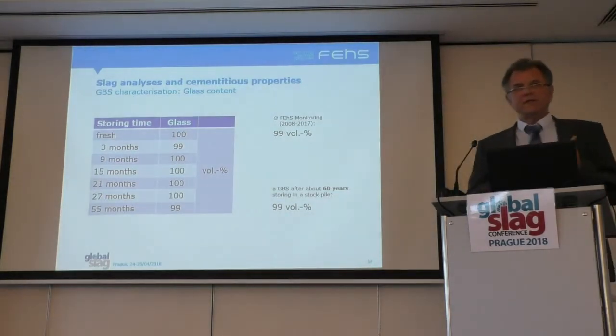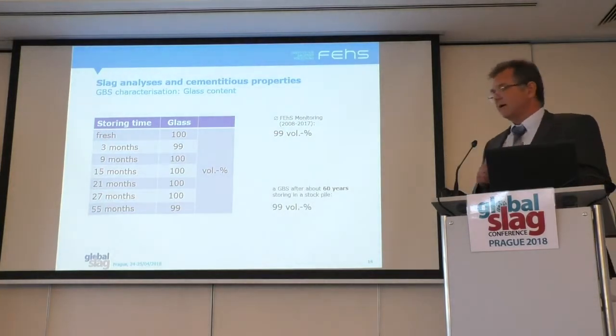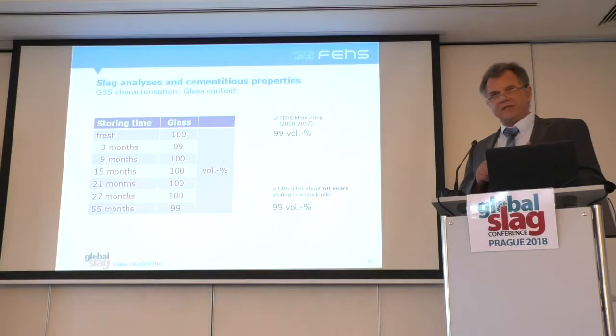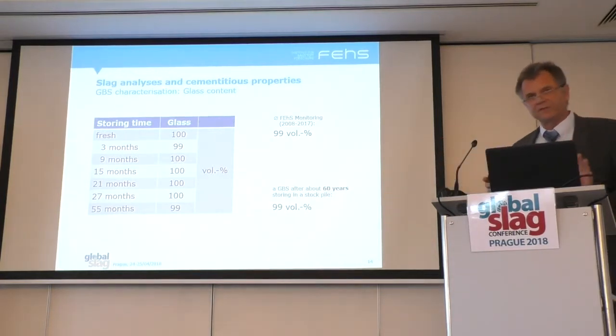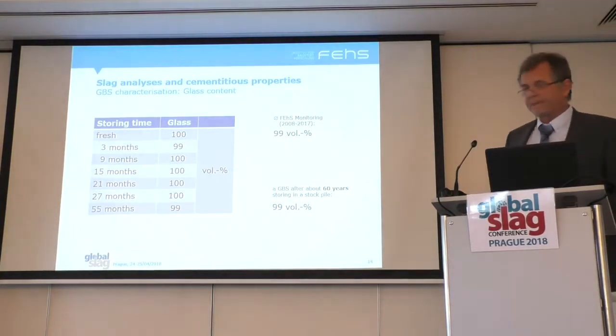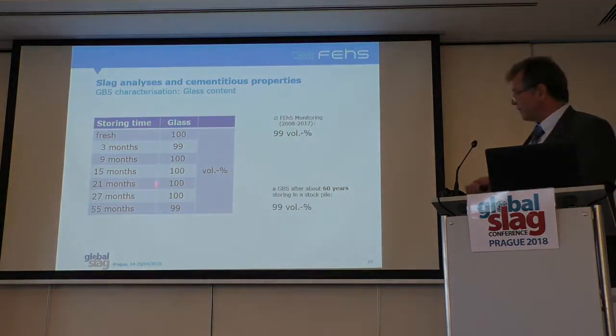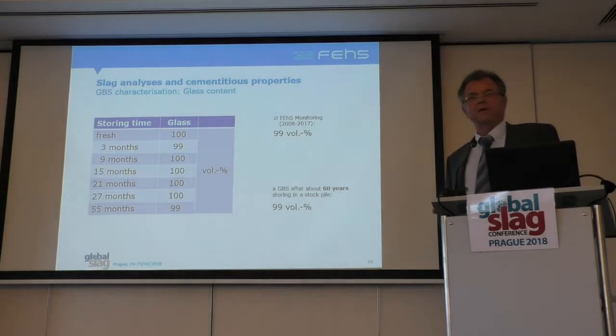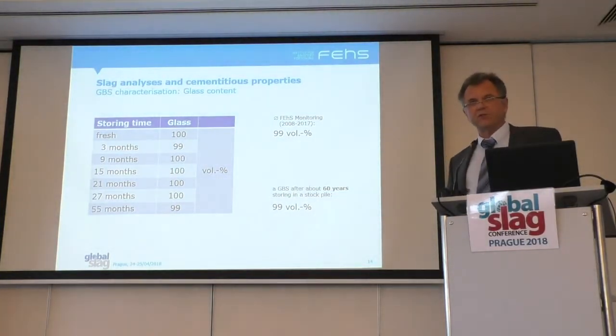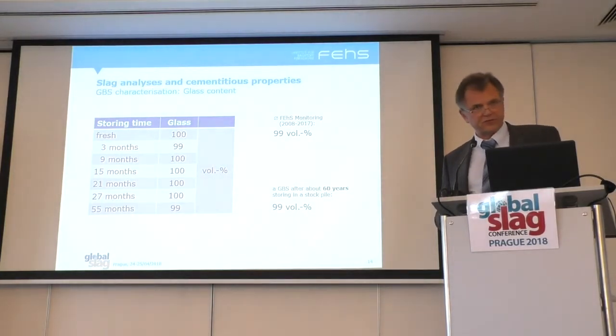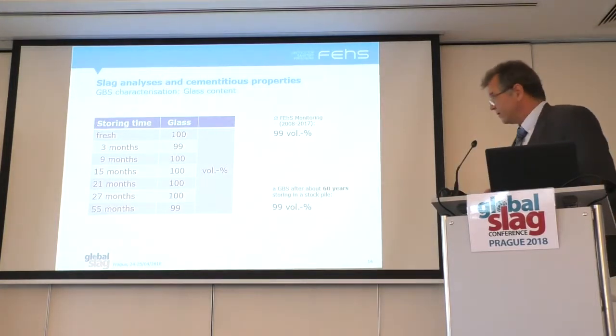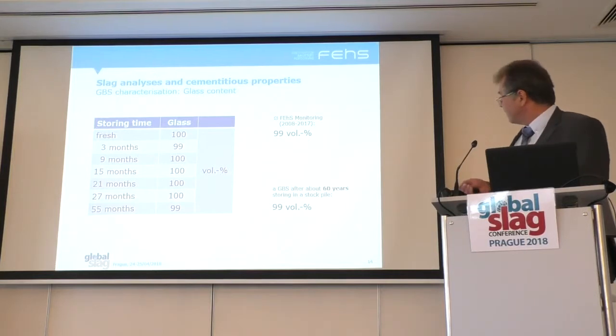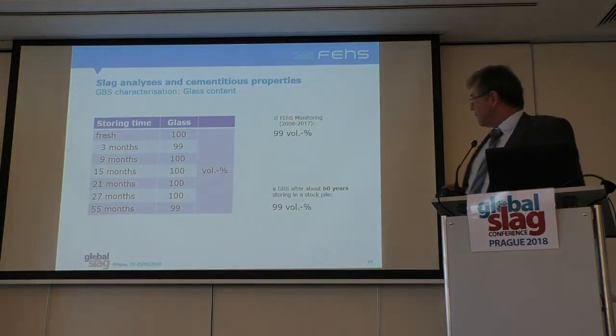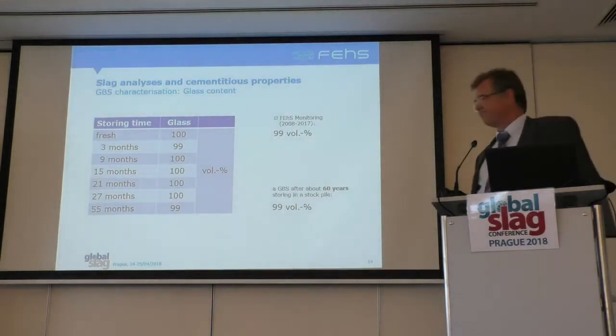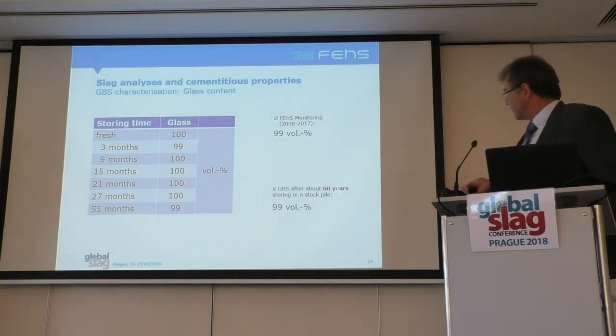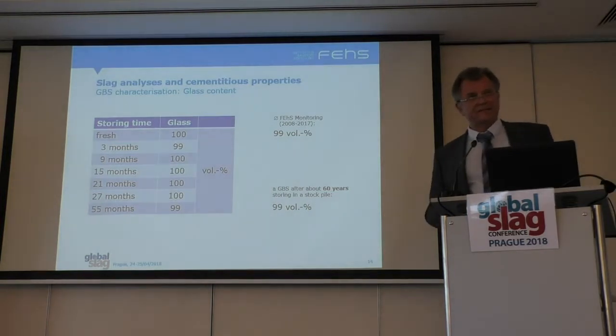Chemistry and glass content, also glass structure, are the important things influencing the reactivity of a GBS, besides technical things like fineness and so on. So let's look at glass content. Glass content, fresh slag and up to 55 months, no change. You cannot find any crystallization products, also not looking at X-ray diffraction. So one basis for reactivity is given also after a long storing time. The average value of our members' GBS is around 100% for fresh slag. And also after 60 years we found in another sample 99% glass.